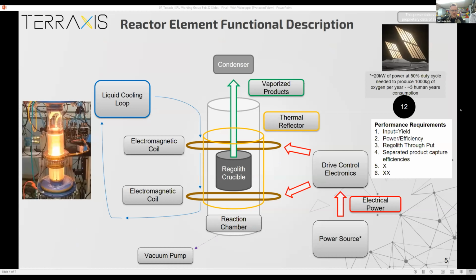So here's a simple functional breakdown of how our reactor works. At the heart of the reactor, we have a high temperature crucible, which regolith is deposited into. That crucible sits within a reaction chamber, which is maintained at a, I would say, mild vacuum. We're talking around 100 Pascal range, maybe a little bit lower or higher, depending on what you're specifically doing. We receive power from a power source, which in our lab is a simulated PV power supply, which then goes into our proprietary drive control electronics, which then drive a series of electromagnetic coils.